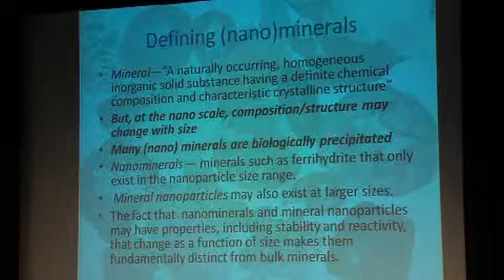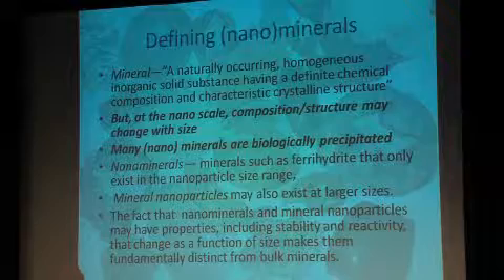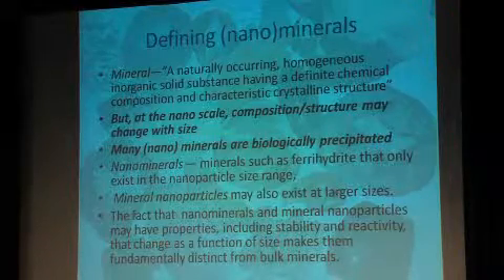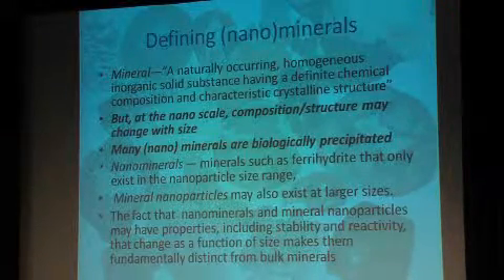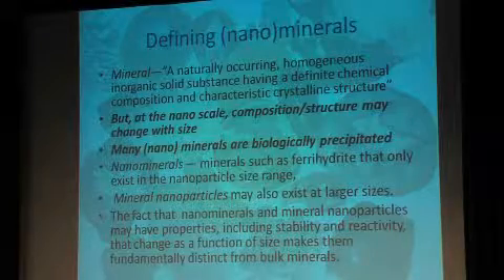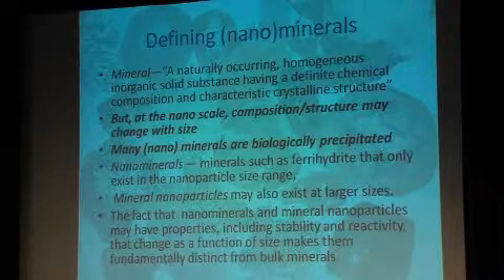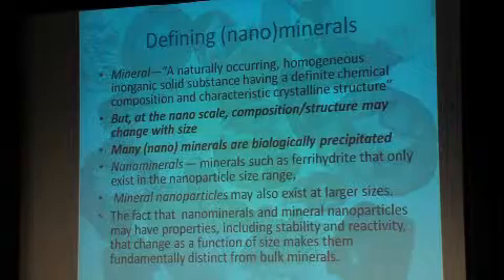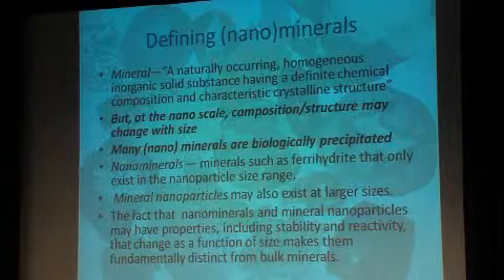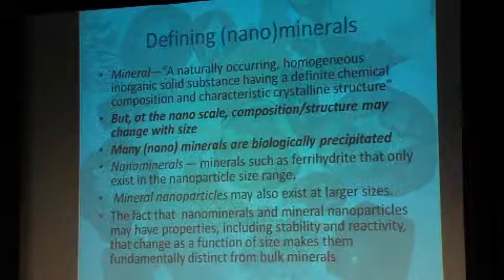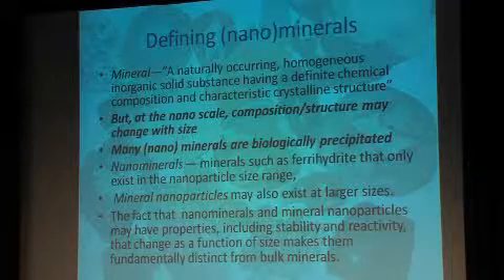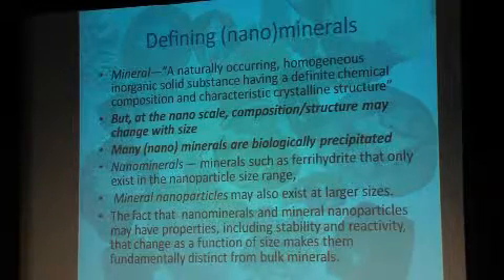function of size. So if we've got the mineral hematite, everybody knows the mineral hematite if you work in my field, okay? And if you try to apply this definition to it, when you get down to nanoscale size, its structure and composition change with size. It's not homogeneous, it's not the same. It's still hematite, but is it really? Does it fit the definition of a mineral or not?